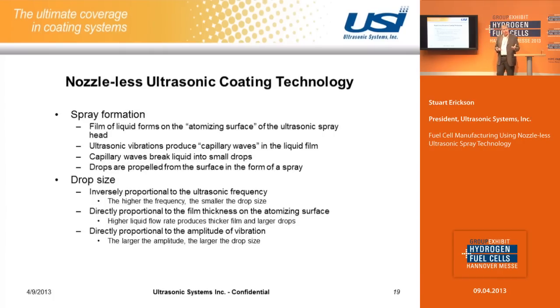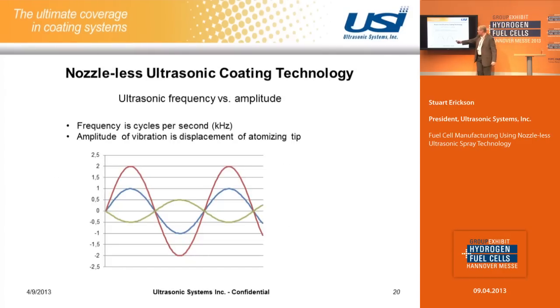The drop size generally with ultrasonics, the higher the frequency, the smaller the drops. However, you can also adjust the amplitude of vibration of the ultrasonic head. It's like a stereo that's playing a single note that you can't hear, but you can turn the volume up louder, turn it down, and you can increase or decrease the amplitude of vibration and therefore influence the drop size of the coating that you're spraying as well. So generally, the larger the amplitude, the bigger the drops. Also, the higher the liquid flow rate going to the atomizing surface, the bigger the drops. So there's many different factors that influence the drop size of an ultrasonic spray device. And this basically just illustrates an ultrasonic frequency, but changing the amplitude. So you have a low amplitude or a medium or a high amplitude of vibration for the same frequency.